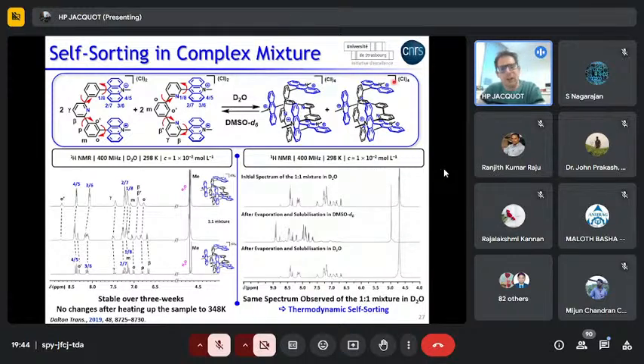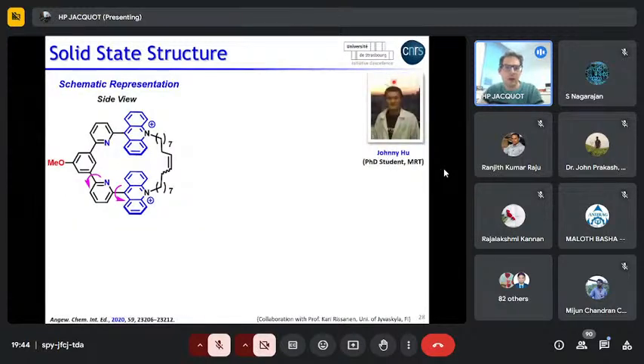Also, what we see is that we are very far from the initial goal, which was to do some host-guest chemistry, mixing two compounds to form a host-guest complex. What we have instead is self-complementary behavior. So if you want to prevent the dimer formation, what you have to do is form the corresponding macrocycle. And this macrocycle was actually made by my former PhD student, Johnny Hu. He was very talented. Johnny made the macrocycle under Grubbs conditions. That was the last step to form this double bond. The yield was 98% because the macrocycle precipitates from DCM, which was the solvent used.